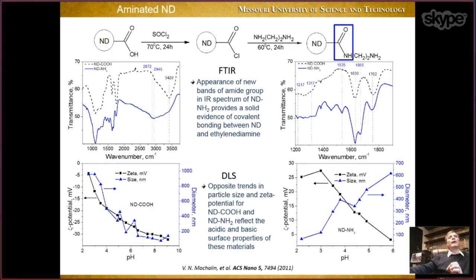So our goal was to focus attention on the peaks characteristic for this amide bond because this bond was not present here. Okay, and we all know very well where the signals of the amide group are. So those are the well-known amide 1, amide 2 bands in IR spectroscopy. So we focused on this range of the wave numbers, and you can clearly see that these amide 1 and 2 vibrations now appear here as a small peak and another peak here, and these peaks are not present in our carboxylated nanodiamond. So now this tells us that we formed covalent bonds between nanodiamond and this diamine, okay?